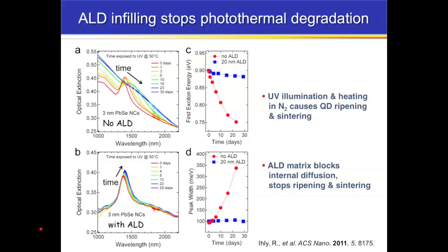If you take a film of quantum dots and you expose it to UV light at an elevated temperature, 50 degrees, 100 degrees, something like that, and you do this in nitrogen, what you see is the first exciton feature is going to redshift and it's going to broaden until basically it bleeds completely into the background after some amount of time at these conditions. So after about, say, 15 days or something like that, you've basically lost this feature.